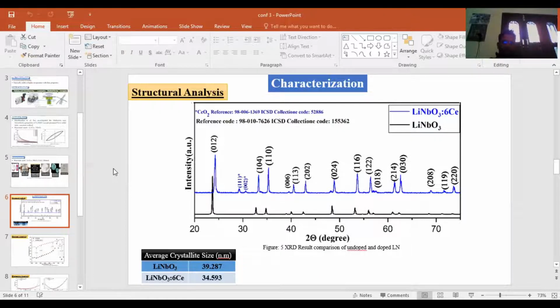And also I calculated the average crystallite size, and for the pure lithium niobate it is 39.287 nanometer, and for 6% cerium doped lithium niobate it is 34.593 nanometer, which is decreased.